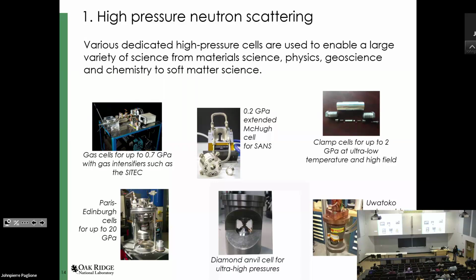The next breakthrough were then the so-called Paris-Edinburgh cells, named after where they were invented. So they are very big presses, 200-ton presses in some cases, where you have sufficient sample volume to do experiments up to 20 GPa at most reactor sources, at most neutron sources, really. We have been pushing the diamond anvil cells to achieve even higher pressures. And then there's also development in a whole range of other cells, like this Paris-Edinburgh cubic cell here, which is a multi-anvil cell that can be cooled.